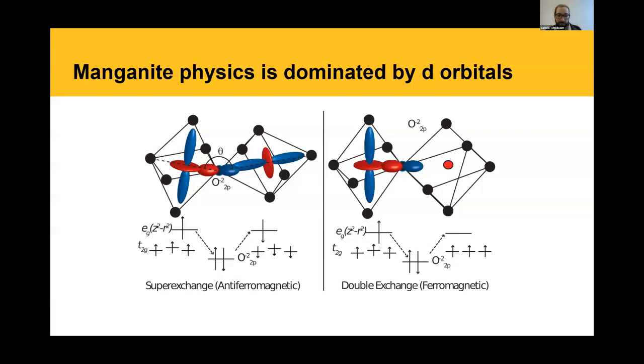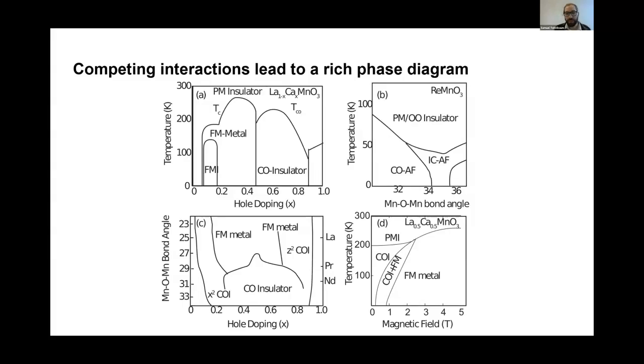The way that you balance between the two normally is you would change the doping, or you would change the manganese oxygen manganese bond angle. Or you would change the temperature. And so depending on what temperature, hole doping, and bond angle you have, you can end up with all sorts of different states. You can end up with charge ordered insulators, which is what we're going to start with in this talk. You can end up with ferromagnetic metals, which is what we're going to end with after photoexcitation. You can end up with paramagnetic insulators, which is essentially the disordered sibling of the charge ordered phase. And you can end up with mixed order phases.